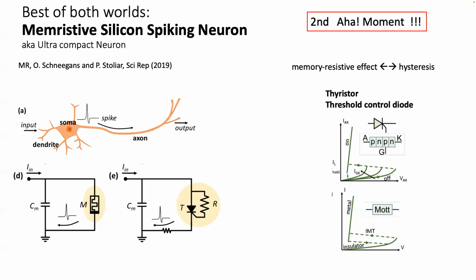To relax, you have to lower the current beneath what is called a holding current, where this depletion layer is formed again because there is very low density of electrons. So there you have hysteresis, and this hysteresis is qualitatively the same as what we observe in Mott materials. So the thought was, if we can make a neuron with a Mott material, we should be able to make a neuron with a thyristor. And the answer is yes.